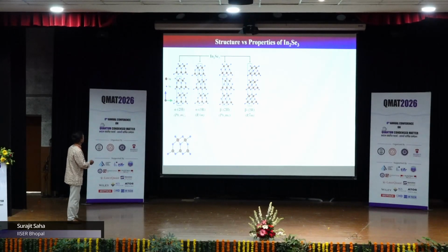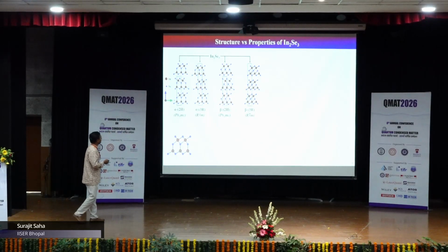In this polymorph, this stacking, which we call alpha, and the other is beta. You can see in alpha stacking, we have the tetrahedral and octahedral coordinated indium stacked as 2 or 3 layers. Then this becomes the 2H structure, and this becomes the 3R structure. But on the other hand, in the beta, what we have is only octahedrally coordinated indium.